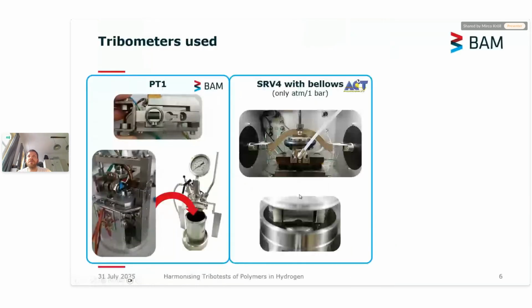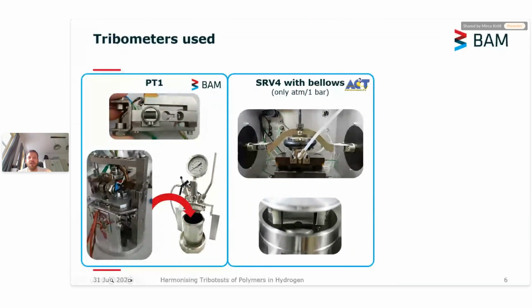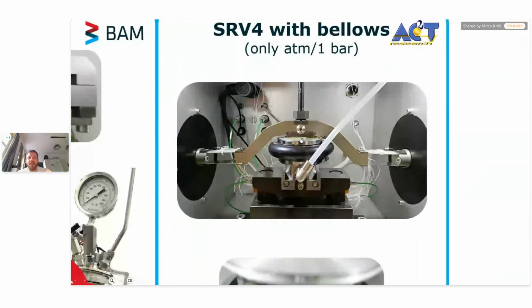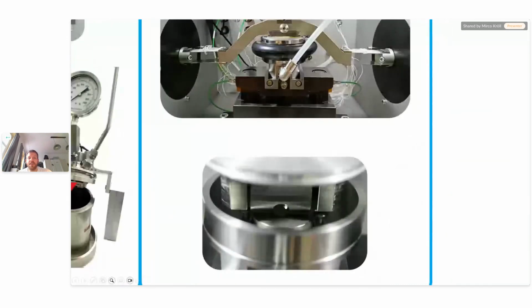Another tribometer we used in our project was an SRV4-based tribometer in Wiener Neustadt at AC2T. You probably all saw sometimes an SRV4 or SRV setup. So you know that, and what AC2T was doing, they built a bellow, a rubber, let's say, balloon around the tribological contact where they introduce hydrogen into that, let's say, contact. And due to the fact that it's a rubber balloon, you can test at atmospheric pressure or 1 bar with hydrogen. And then you can see here the polymer sample moving over the steel disc.